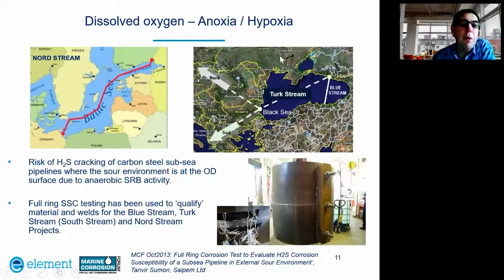To qualify pipelines which have been put across the Black Sea, there's the Blue Stream pipeline that was put between Russia and Turkey about 20 years ago, and also the Turk Stream or South Stream pipeline that went between Russia and Bulgaria more recently. And then there are the pipelines in the Baltic Sea, the Nord Stream pipeline from Russia to Germany. These were subsea pipelines where full ring testing was carried out to qualify the material for welds, and these tests were conducted for the Blue Stream, Turk Stream and the Nord Stream projects.